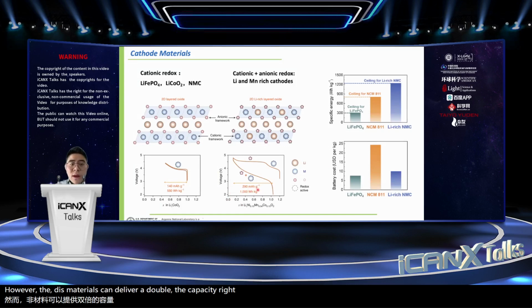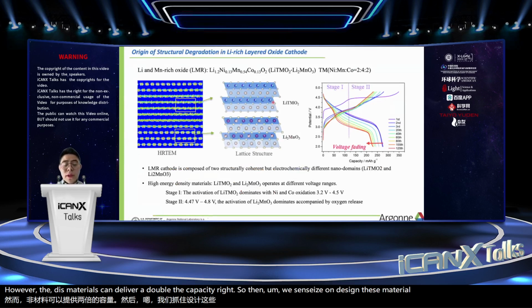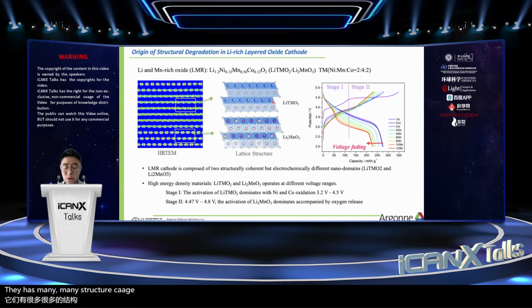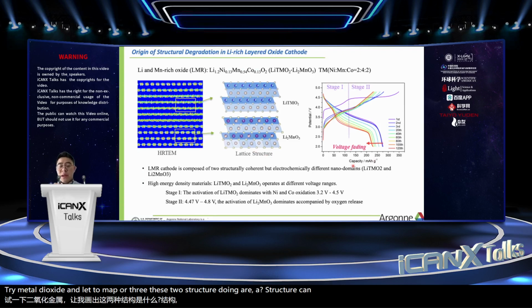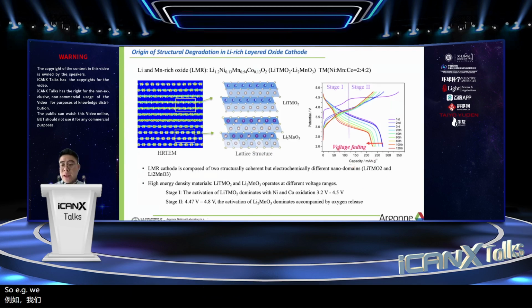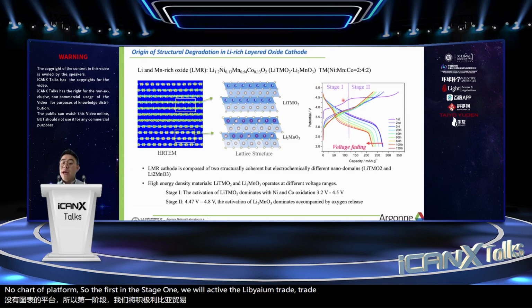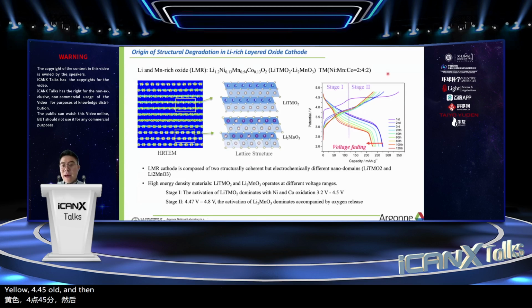Right. So then we synthesize or design these materials. They have many structure characteristics. First, they have two structure domains: lithium metal oxide and the Li2MnO3. These two structure domains are structurally coherent and electrochemically different. So, for example, we will look at the charge discharge profile. In the first charge, they have two charge platforms. In stage 1, we activate the lithium metal oxide below 4.5 volt, and then we will have a higher voltage platform for Li2MnO3.